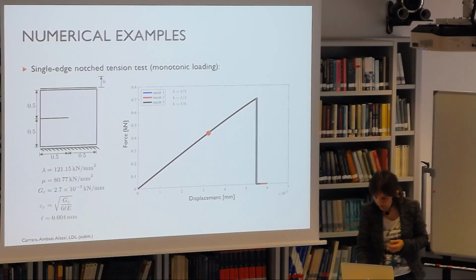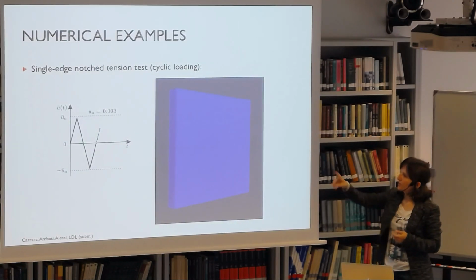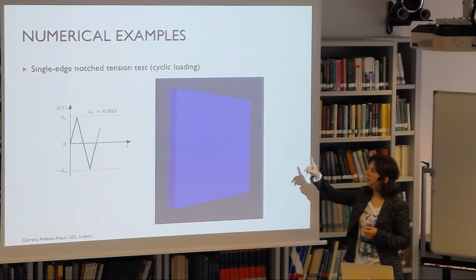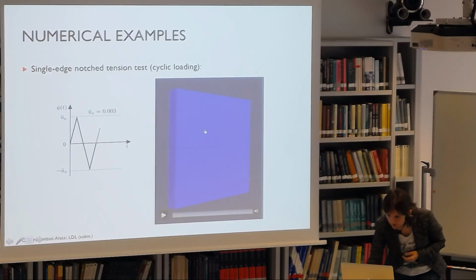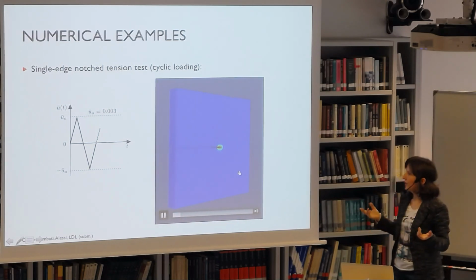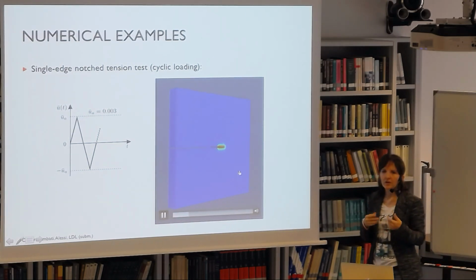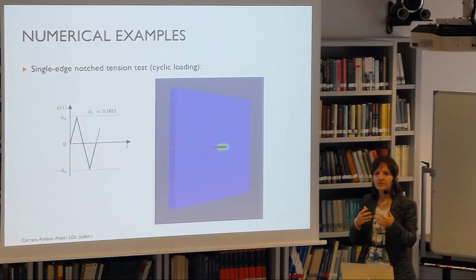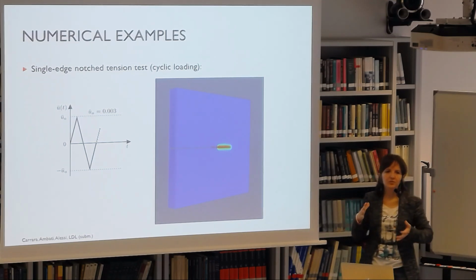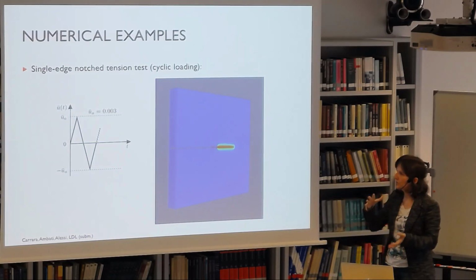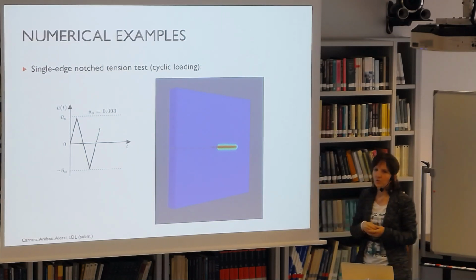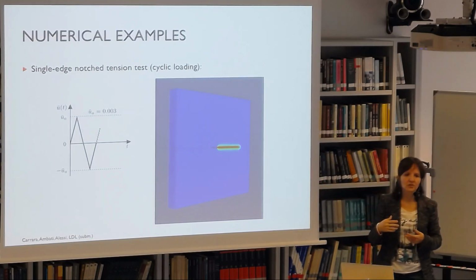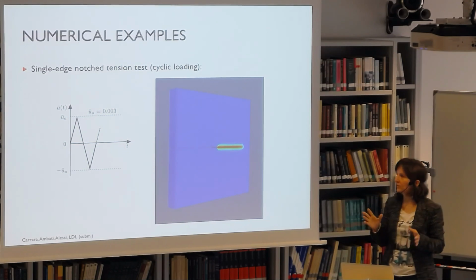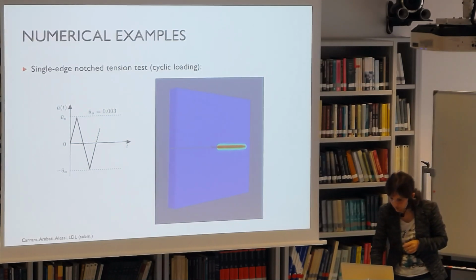So we'll be applying cycles of that shape, so linear cycles, and what will happen is that the basic effect is that as the alpha bar is cumulating, then f of alpha bar is decreasing, so the fracture toughness is decreasing, and so the crack will continue propagating over time due to the fatigue effect. So this is, let's say, the basic feature that we wanted to reproduce.